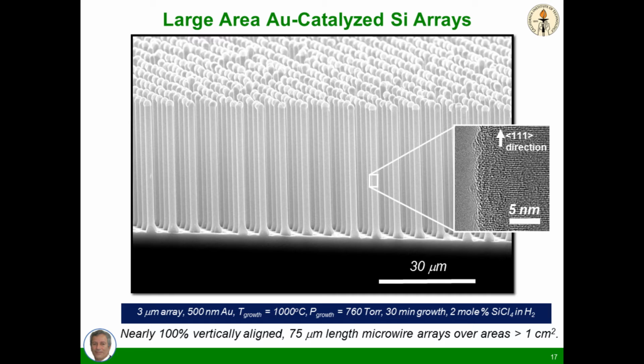And so we can use very cheap material because they don't have to go all the way, and the liquid is the perfect conformal contact to infiltrate this in a way that if you tried to make an ohmic electrical contact to such a device, it would be arguably manufacturably impossible. We showed that worked. We showed we could make good solar cells that could oxidize and reduce materials out of cheap silicon in this microwire array.